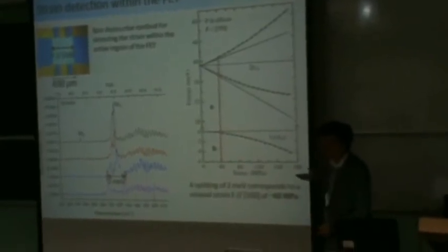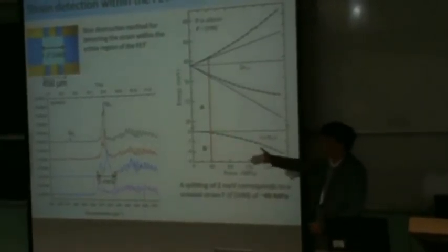Yeah, I didn't actually describe that because it's not very beautiful. It was basically what happened is I had this bottom sample, I had it poorly mounted. And so basically I just bent the sample mount and popped the sample off and then thought, okay, it's ready to go, and stuck it back down and happened to be a whole bunch of strain in there. But with this in mind, it's quite easy now to set up a system where this strain is adjusted. So you can actually live modify the strain of the device.